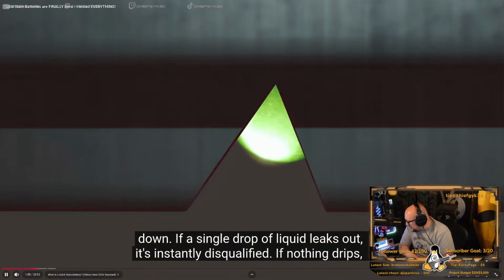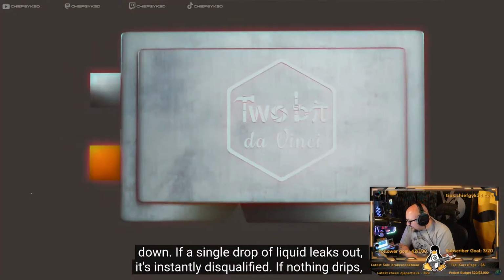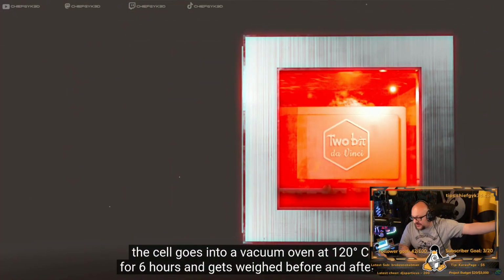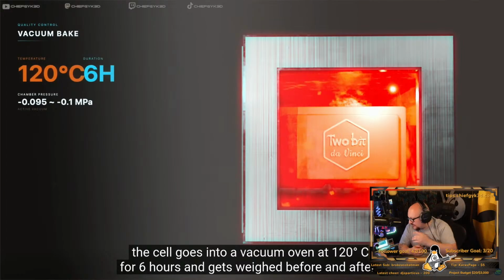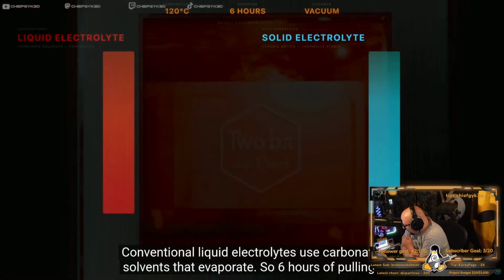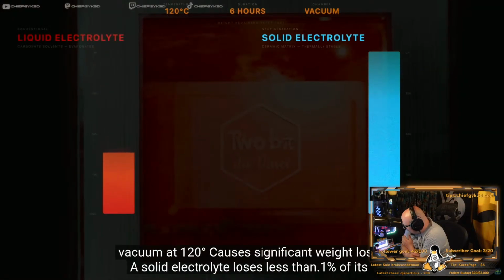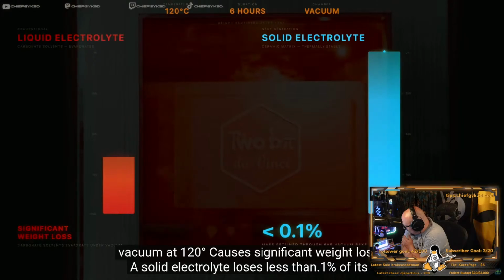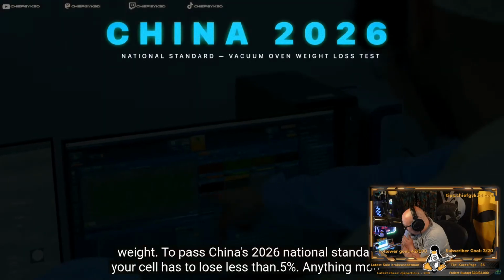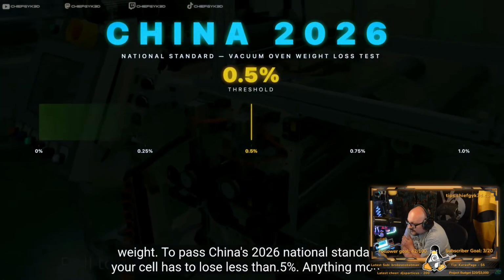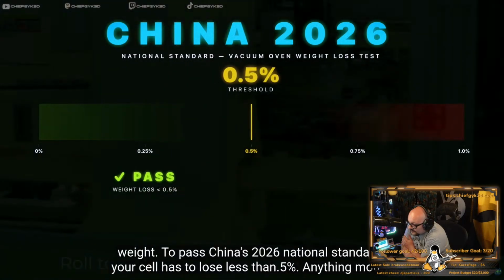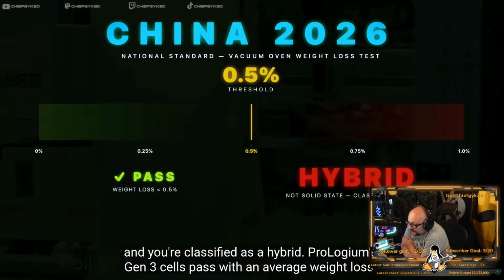If a single drop of liquid leaks out, it's instantly disqualified. You're back. What happened? Oh, the Windows machine that runs the stream crashed. There's a 2 PC setup running the stream. The cell sits at 120 degrees Celsius for 6 hours and gets weighed before and after. Carbonate solvents evaporate, so 6 hours of pulling vacuum at 120 degrees Celsius causes significant weight loss. A solid electrolyte loses less than 0.1% of its weight. To pass China's 2026 national standard, your cell has to lose less than 0.5%. Anything more, and you're classified as a hybrid.